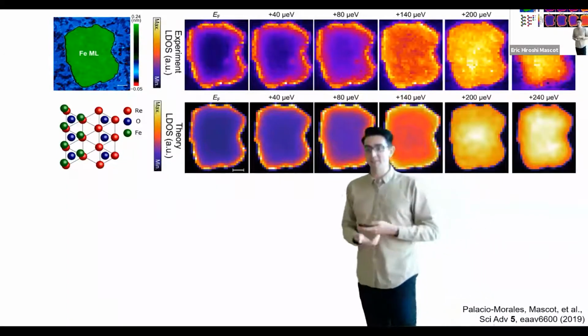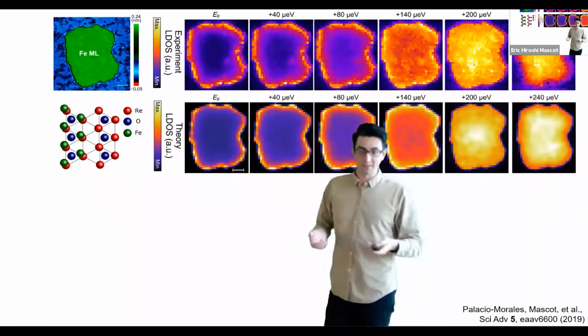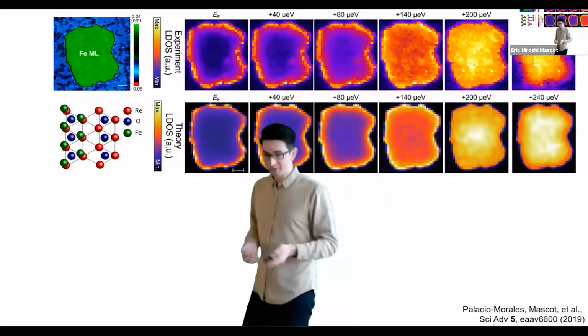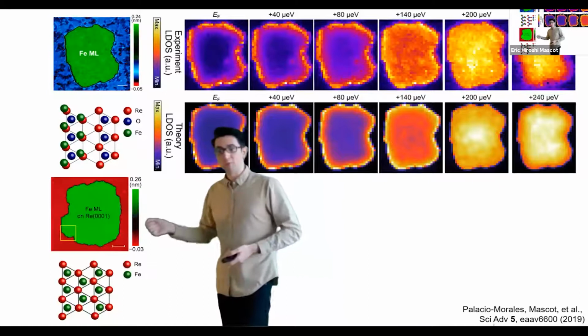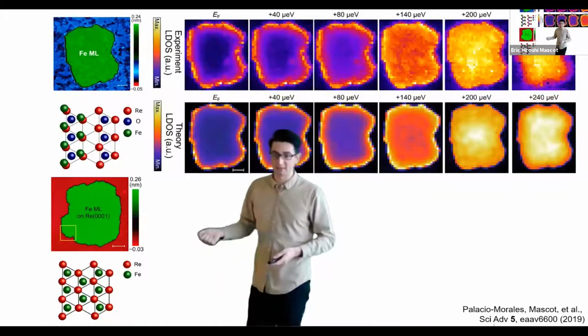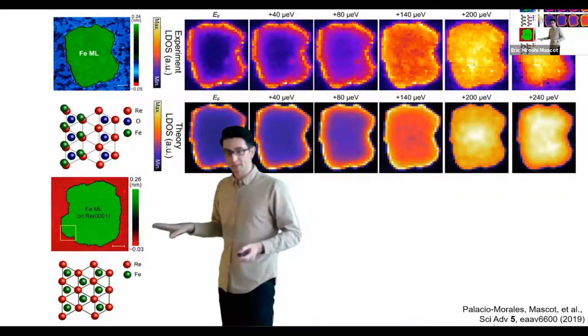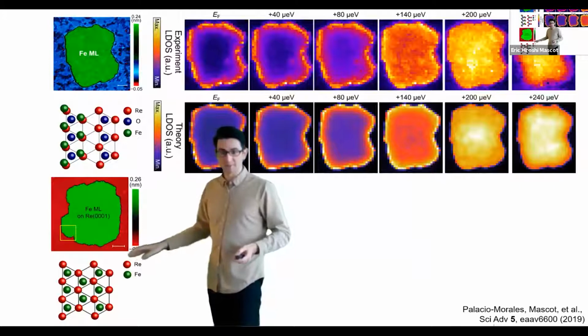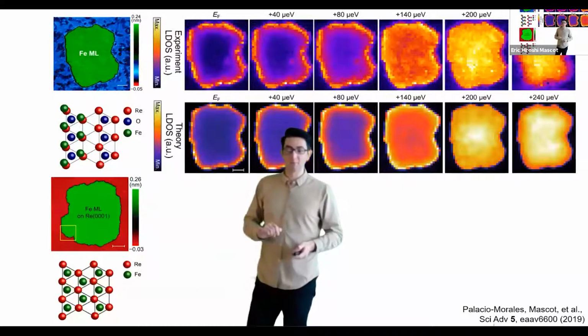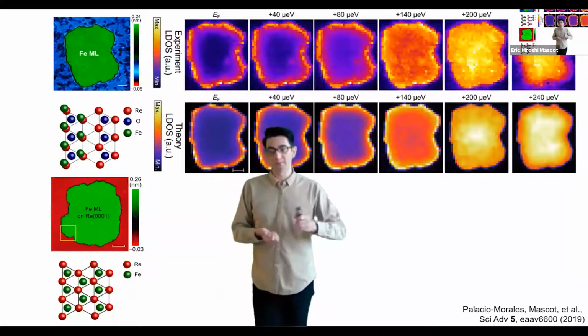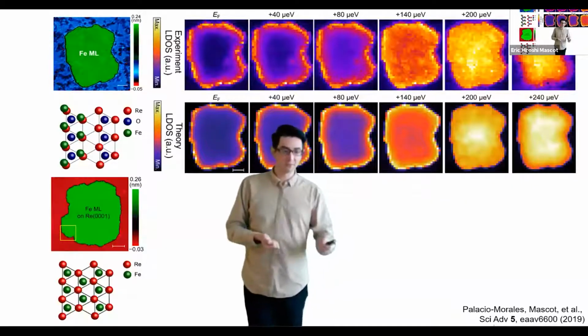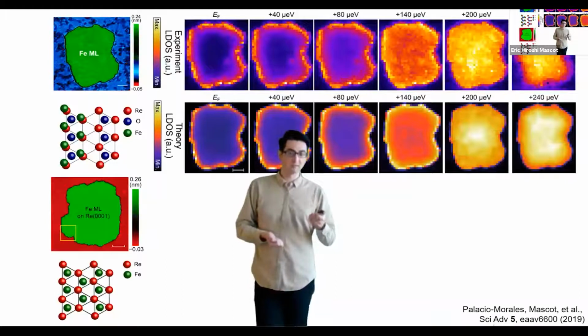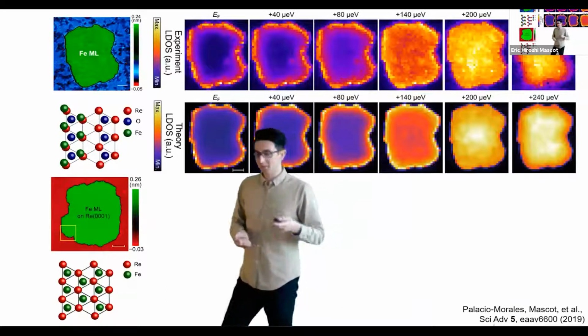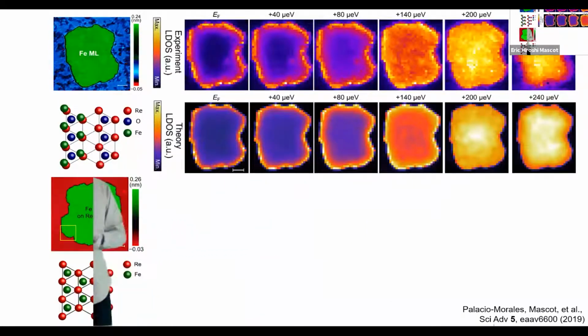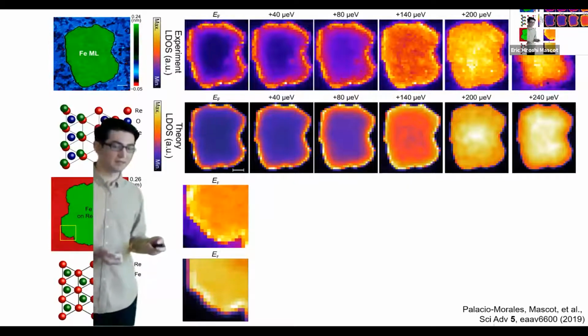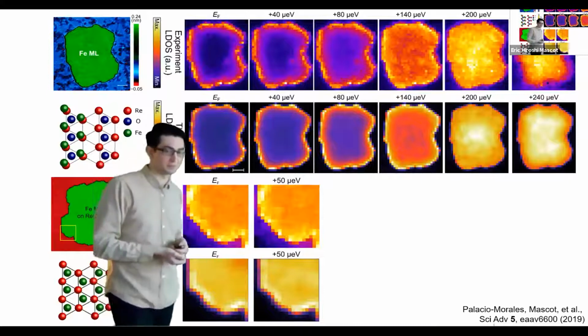And an important check is to see if this holds for other samples, for different islands. One interesting sample was this iron monolayer, which did not have the interface oxide layer. And in this case, what happens is that because the oxygen atoms aren't in between the rhenium, instead the iron atoms fall in between. And so when we take our model and move the iron atoms in between the rhenium atoms, what we found is that we close the energy gap and we get a trivial topological phase. And so when we calculate the local density of states, since we close the energy gap, all we see are bulk states inside the island for both theory and experiment for all energies.